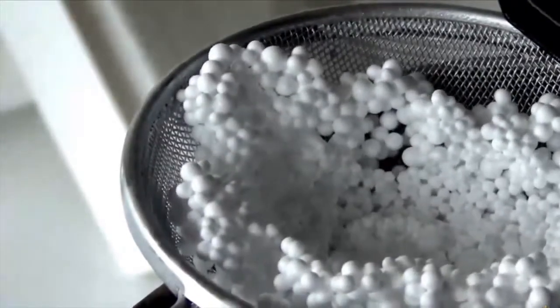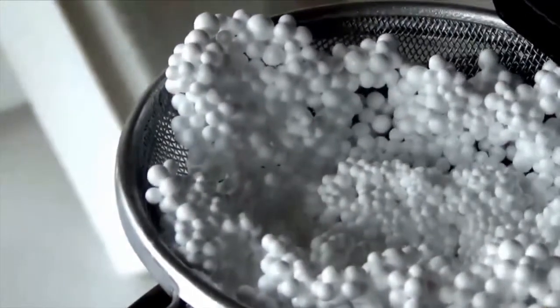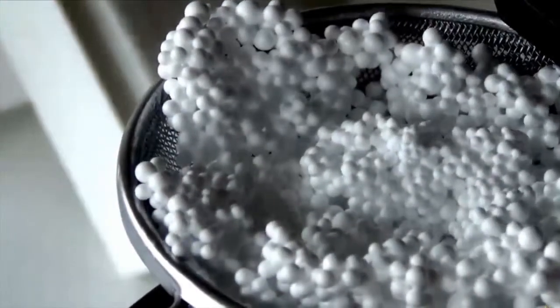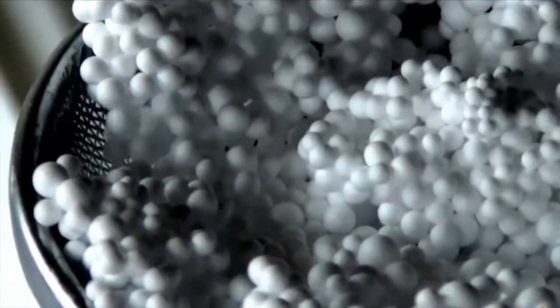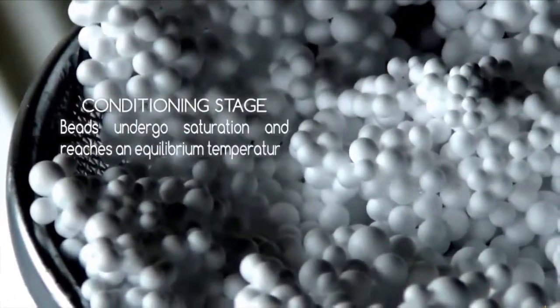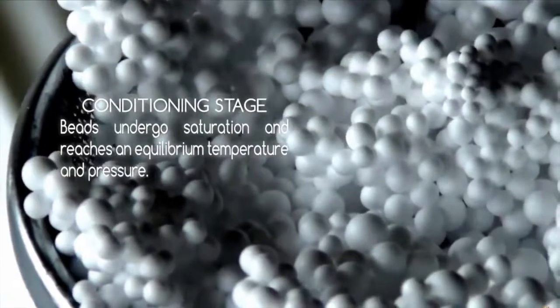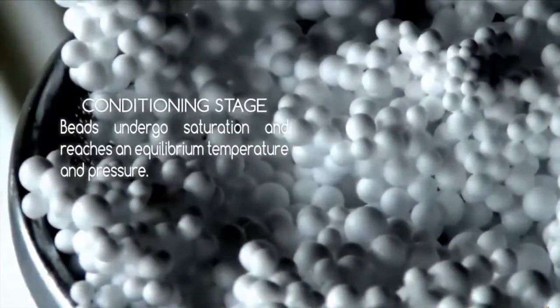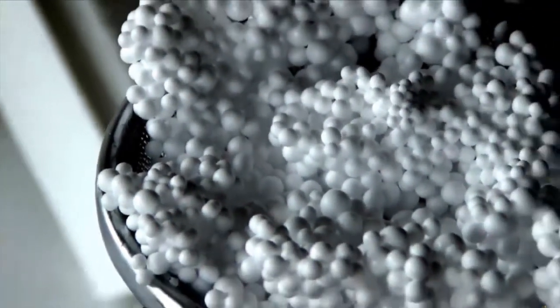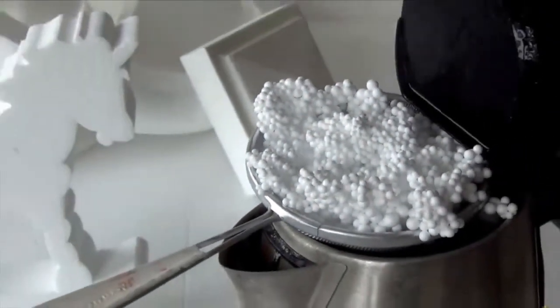The London dispersion forces of benzene is what makes the styrofoam foam. This polymer is made in three steps. Pre-expansion is where the pre-foaming agent found within the polymerization beads starts to boil and beads are expanded between 40 to 50 times their original volume. Then the conditioning process occurs and the beads reach equilibrium temperatures and pressure. Finally, the beads are placed within the mold and again reheated with steam. The pre-foamed beads expand further, completely fill the mold cavity and fuse together. The beads are molded to form foam blocks and customized products. When molded, nearly all volume of styrofoam is 98% air.